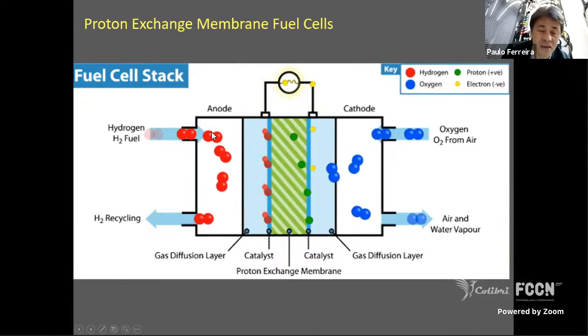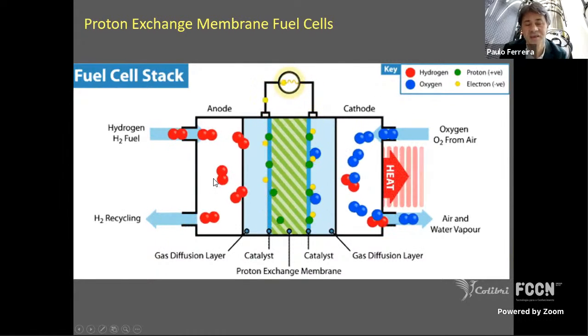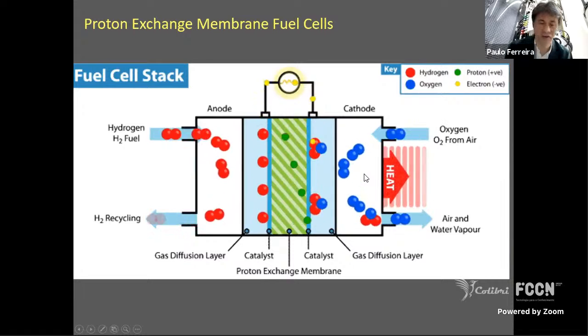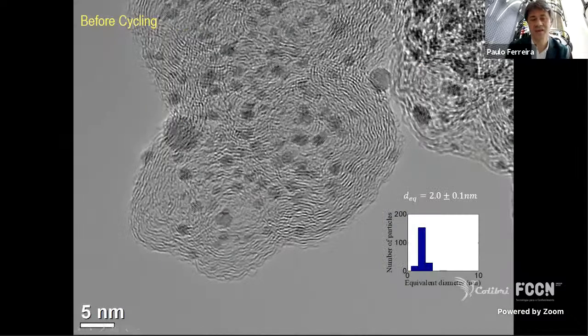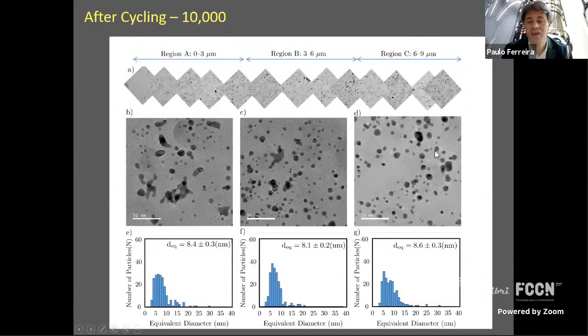At the heart of these fuel cells are catalysts sitting on the anode and the cathode. If you look in detail, before you cycle this fuel cell, you see the particles here in dark. They are very small. You see here the particle size distribution, about 2 nanometers. The rest is carbon, which is a support where you see the particles sitting. The problem is that when you start cycling this, you get a huge increase in the particle size. Remember, it was about 2 nanometers. Now it's about 8. And you see from these images that the particles have grown a lot.